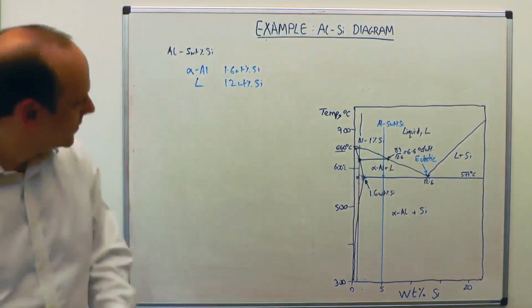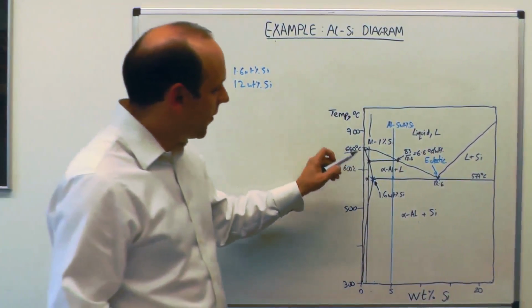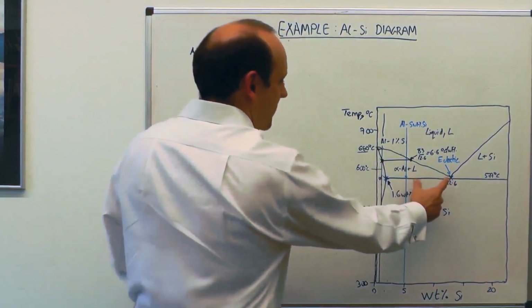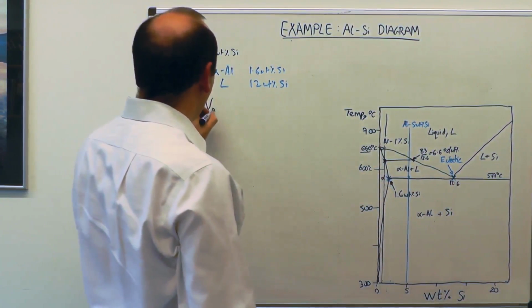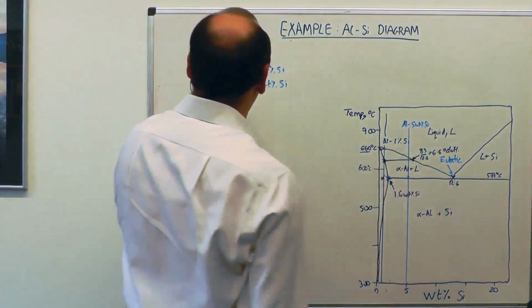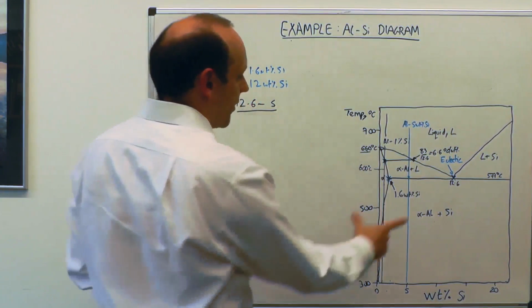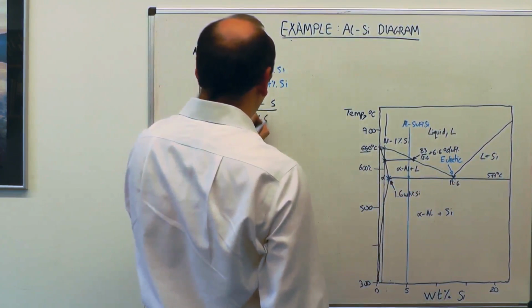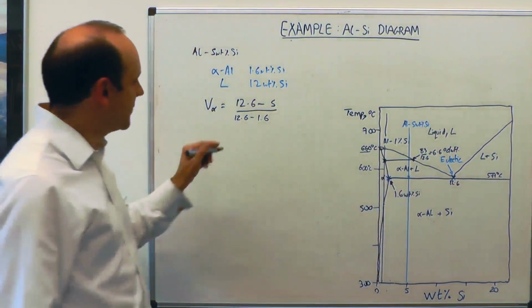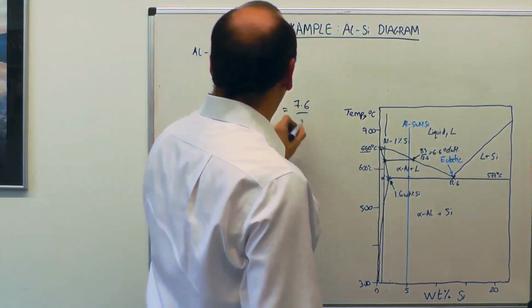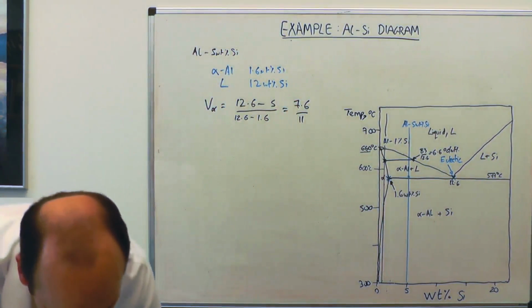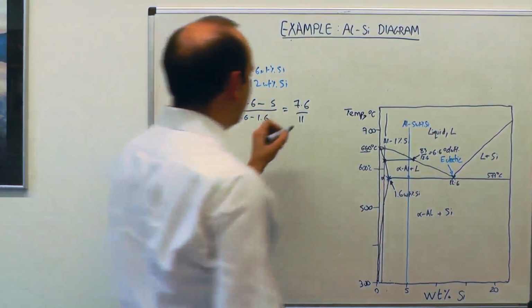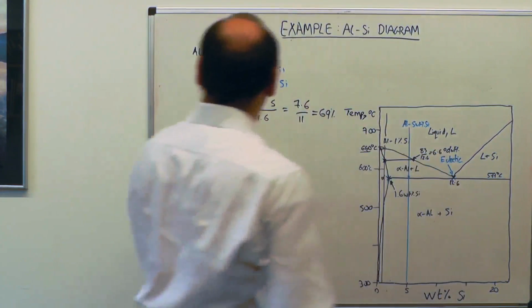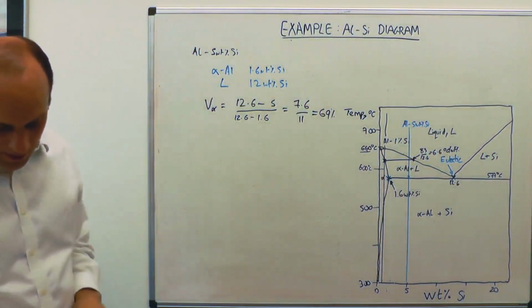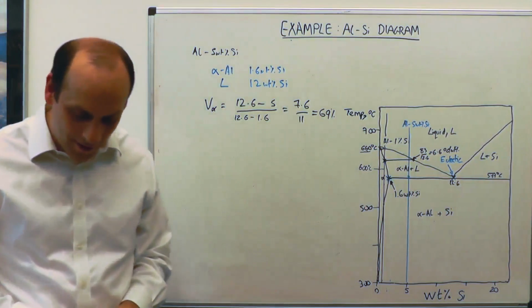And if we want to calculate the volume fraction, those are the two phases, those are their compositions, we could say the volume fraction of alpha is the opposite little distance divided by the whole distance. So the volume fraction of alpha from the lever rule is the opposite little distance, that's 12.6 minus 5, divided by the whole distance, that's 12.6 minus 1.6. So that's 7.6 divided by 11, that's 69%. So that's our volume fraction of alpha phase. That's question 9 done.